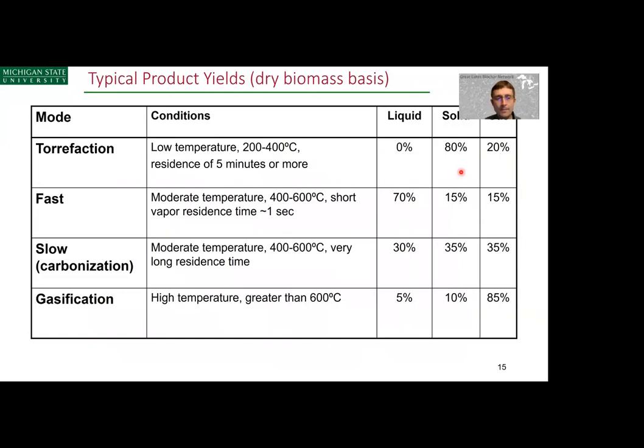So just in review, starting with torrefaction, this is the low temperature version of pyrolysis. We do get a relatively high solids content. That material is really for displacing coal at coal-fired power plants. Though you get a high solids yield, there's still a lot of unreacted biomass in the torrefied biomass product that you produce, and that unreacted biomass would include things like carbohydrate polymers, cellulose and hemicellulose. So often we don't consider torrefied biomass as a source of biochar for soils. Instead, we look to fast pyrolysis and slow pyrolysis for doing that.